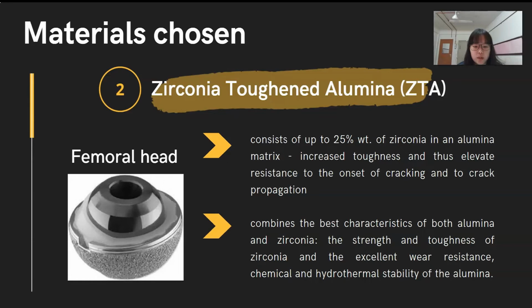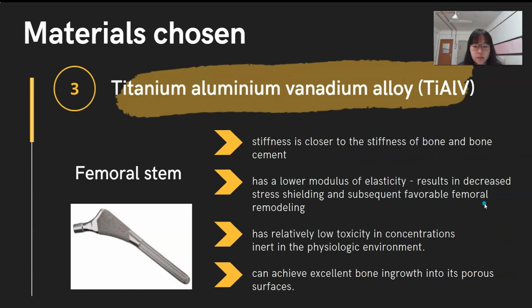This ZTA composite combines the best characteristics of both alumina and zirconia, which is the strength and the toughness of zirconia and the excellent wear resistance, chemical and hydrothermal stability of the alumina. For the femoral stem, the material chosen is titanium aluminum vanadium alloy.